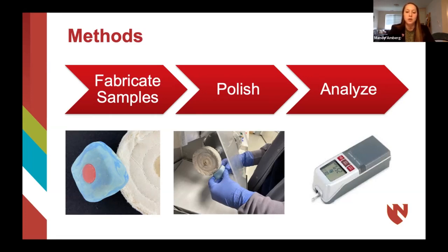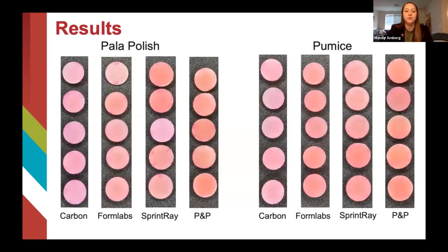Then 3 measurements with the specified devices were taken for surface roughness and gloss for each puck. Data was analyzed using a 2-way ANOVA and Tukey-Kramer statistical analysis. These images show the samples from each group after polishing was completed. The samples polished with Pala Polish are on the left, and those polished with pumice are on the right.